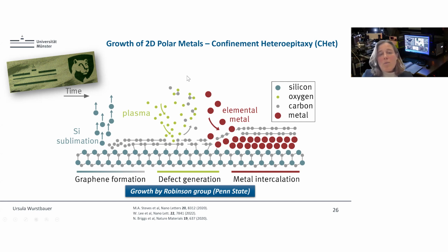If you now open up some windows to this graphene, then you can intercalate something. It's energetically favorable for this material to go into this interface, and then those remaining bonds are released. Gallium likes to bond to the silicon atoms. The process is stopped again by the energetics of the interface, which can be determined.